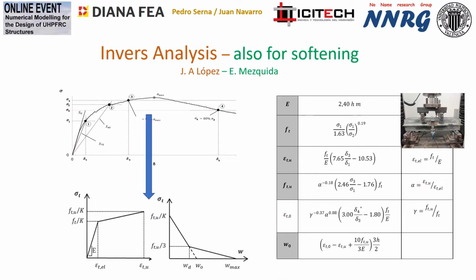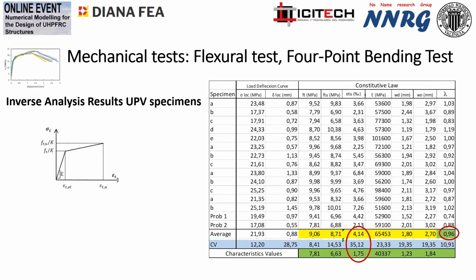Well, we can define the flexural and tensile strength, as Eduard commented before, and those are two important points. If we work on softening or hardening, but also at what level you finish your capacity to control the crack, because in this period you have microcracks if you have hardening, but also if you have softening. Even if you have softening, you have multi-cracking.